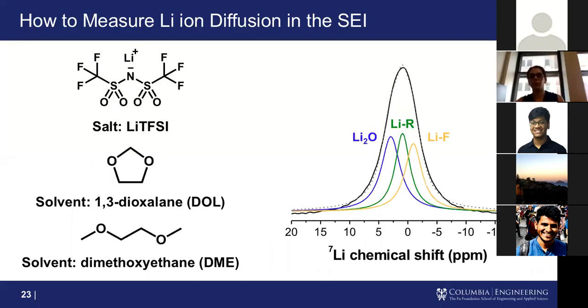So if we do that type of experiment, what we end up getting is these spectra shown here in different colors. This yellow spectrum here is a spectrum that we acquired by passing magnetization from fluorine to lithium. So this is probably lithium fluoride, probably some residual TFSI. Then we have this, what I'm calling LiR, with R just meaning any organic group, but we've acquired this spectrum by passing magnetization from protons to lithiums. So you can see it sort of falls in the middle. And this blue spectrum here is the spectrum that we measured for lithium oxide.